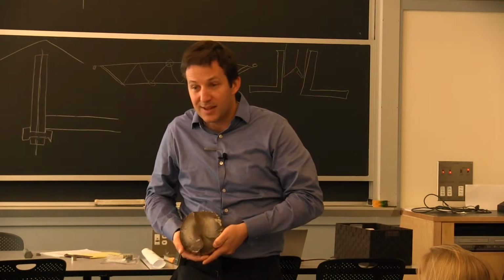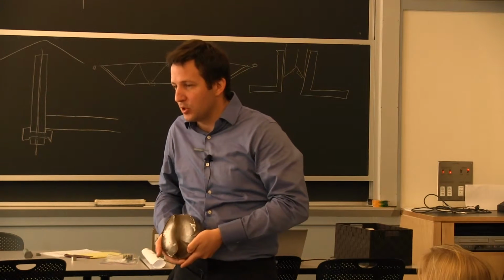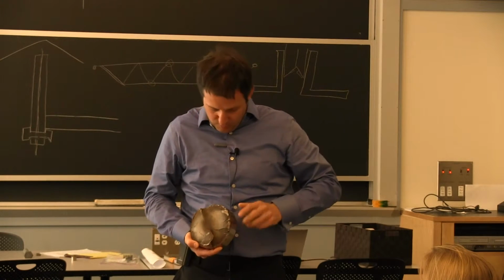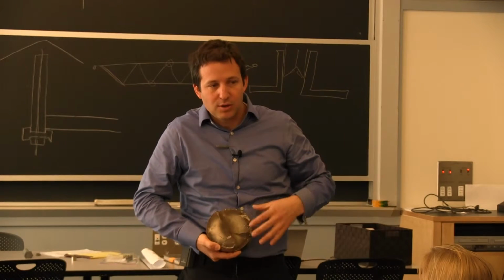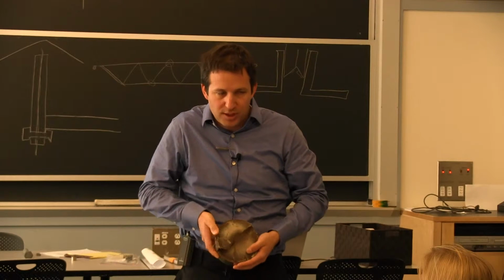When we see those, it's very easy, you don't even need fracture mechanics to say the load was not that high. This is not a problem with load. This is a problem with fatigue, a crack starting around the circumference and a lot of cycles going around turning to grow these cracks.